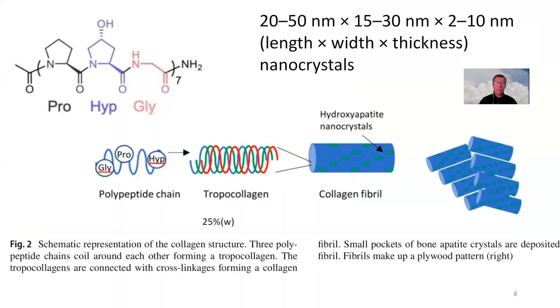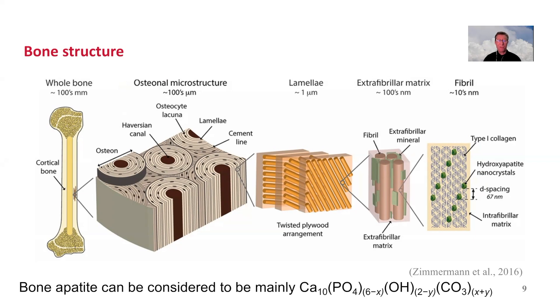Bone contains about 30% collagen, a coiled-up polypeptide mainly containing glycine, proline, and hydroxyproline. This forms fibrils that are intercalated with very small inorganic crystals of calcium phosphate. These fibrils make up a so-called plywood pattern, which in turn makes up the macroscopic bone — somewhat like a brick-and-mortar structure. And it's not just phosphate; it also contains some carbonate and hydroxide in what we call bone apatite.